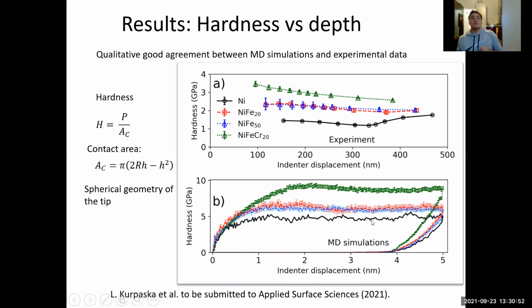Something that I forgot to tell you is that nickel is only one element, and the crystal orientation is 001. But since you have the symmetry and it's based on an FCC unit cell, you do the nanoindentation only once and you don't have problems. Okay, there is a contact area, but since the indenter is 5 nanometers, it's really big. So only one simulation is enough, and the error bars are really small.